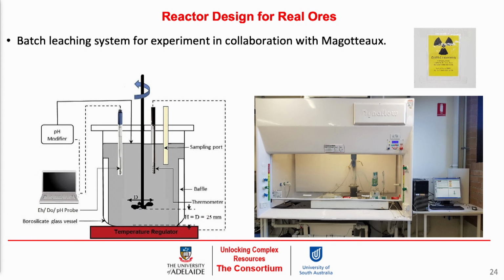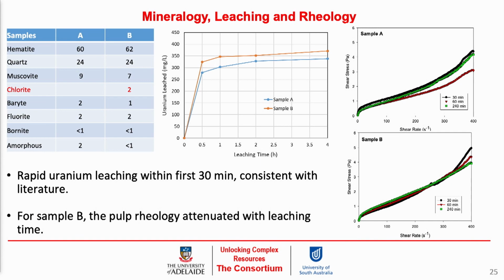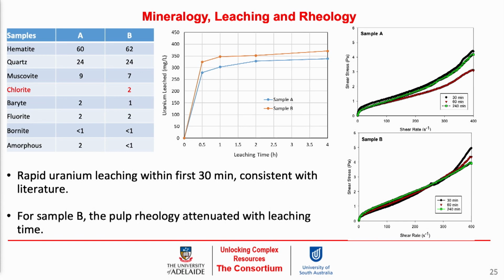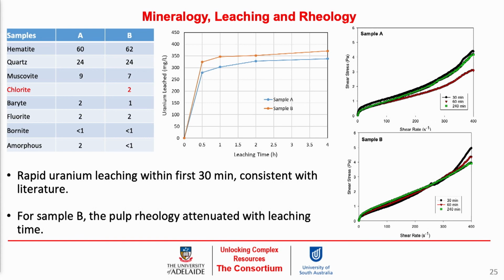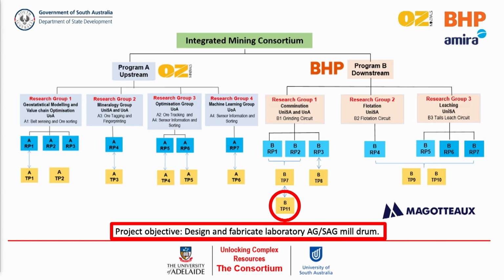We can monitor the solution chemistry whilst we are doing the leaching, and also at high temperature. We've done initial work, definitely all in collaboration with Magotteaux. Initial work on the effects of mineralogy showed that the change in mineralogy in the 2 sample types affected not only the leaching yield, but also the rheological behavior, which varied for the two sample types.